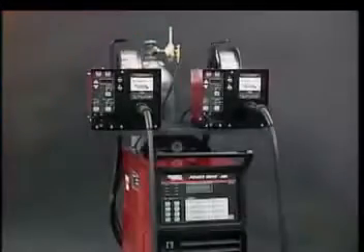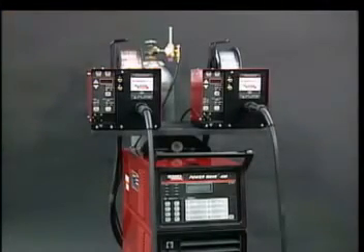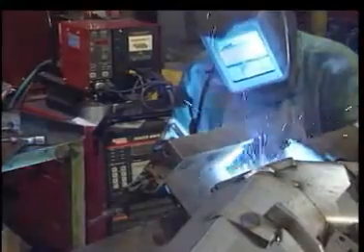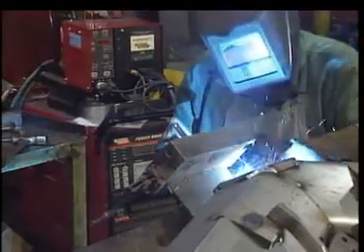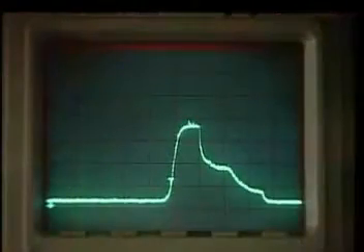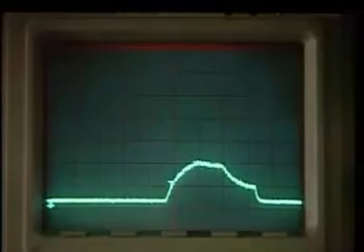That is the major benefit of using the Lincoln PowerWave pulsed arc welding process. The process allows wire feed speeds ranging from 50 to 1,200 inches per minute, and it's virtually spatter-free across the entire range. With precise control of arc dynamics, the PowerWave can be used as a fast-follow process at high travel speeds, or it can be run as a high deposition rate, fast fill process. Precise control of the output waveform varies the arc characteristics.